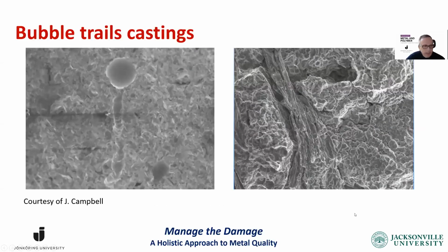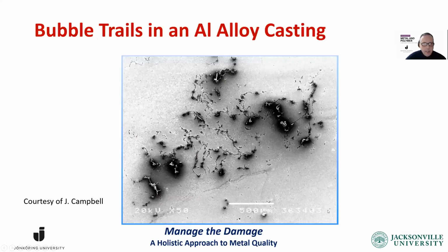Then we see bubble trails. You see on the left-hand side, in a zinc die casting, a bubble trail. You see the bubble at the top, but you see the trail at the bottom. On the right-hand side, you see a trail that looks like an old dry tree. Those are the oxides left behind by the bubble as it gets moved up by buoyancy. And when you come across something like this, it is basically a bubble trail, but you look at it from a different angle. You're looking at it from the bottom up. So these air bubbles are highly damaging to the liquid aluminum, and later obviously to the casting.